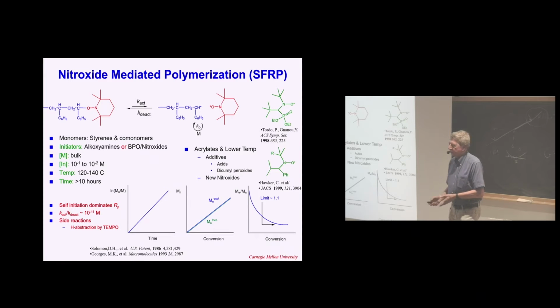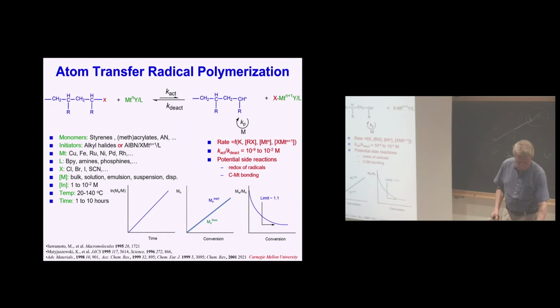So this is really a stable radical because it's stabilized by this phosphorus compound and these t-butyl groups. They changed this ethoxy to methoxy, isopropoxy. Nothing was working as good as this SG1 original one. So under some conditions, you can have also pretty good control. Molecular weights follow this linear development with conversion, and dispersities go down to 1.1 or less.